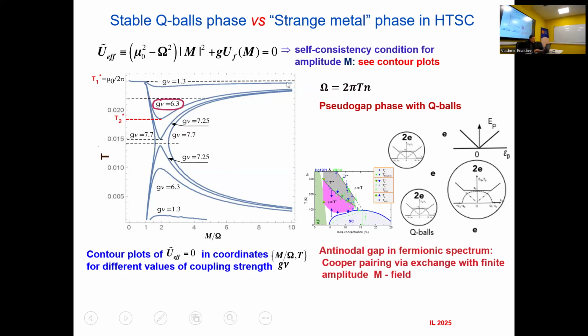So what these plots show you is that when we increase G nu gradually, the solutions of this equation form this different family of curves, and they become deeper and deeper in temperature. And what is also important, for each G nu you have two regions of solutions. One region of solution is close to T star, and another region of solution is close to zero. So you see, it looks very much like the phase diagram of high Tcs because you have a superconducting dome, which is obtained due to this lowest branch for each fixed G nu. And you have a strange metal region, which is obtained for the upper branch of solution for each fixed G nu.